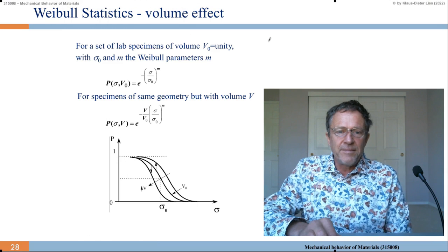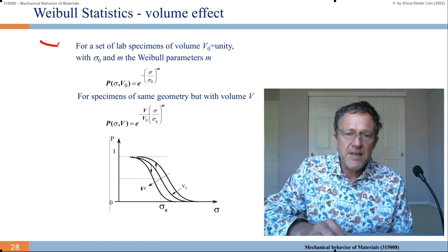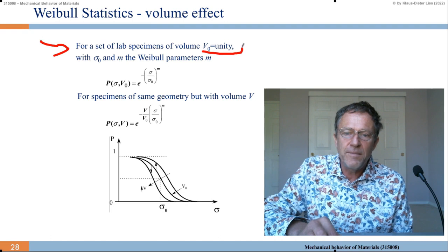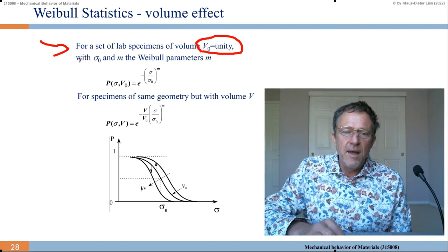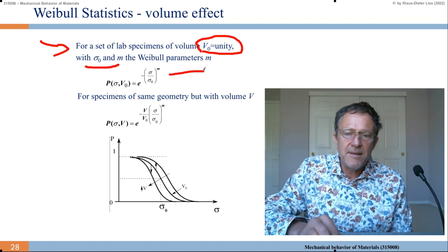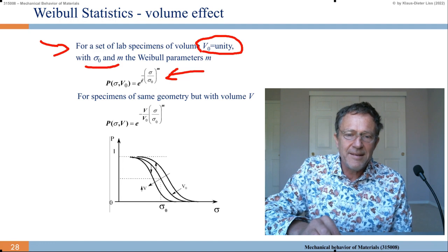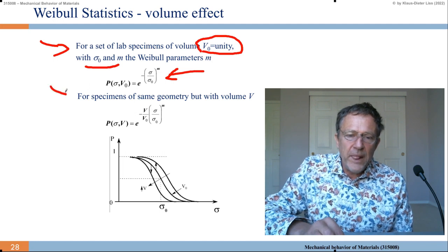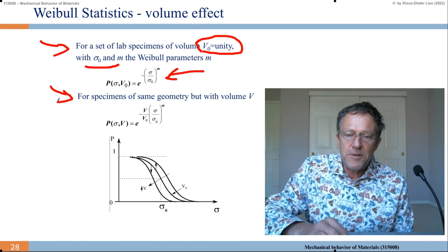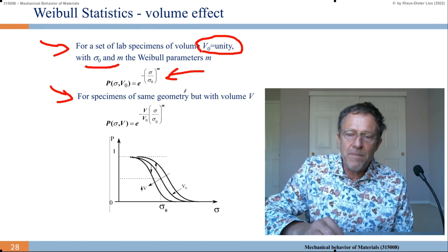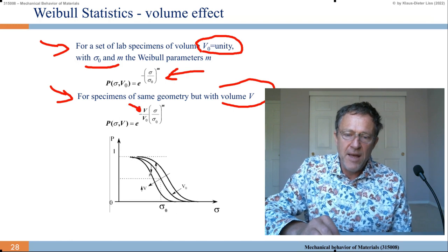Here also, regarding the volume effect, for a set of lab specimens of the volume V0, let's say V0 is unity volume, with sigma 0 and m the Weibull parameters, we get this probability P of sigma V0 as hat. So for V equals V0, we get sigma over sigma 0 to the m. Now, if we take the same kind of specimen, the same geometry, but a larger or a different volume V, larger or smaller, then of course it scales with V over V0 in the exponent. And that is shown here.